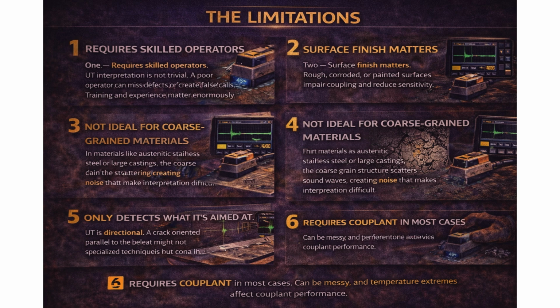5. Only detects what it's aimed at. UT is directional. A crack oriented parallel to the beam might not reflect energy back. Technique selection is critical. 6. Requires couplant in most cases. Can be messy, and temperature extremes affect couplant performance.